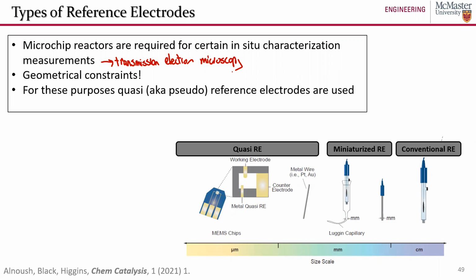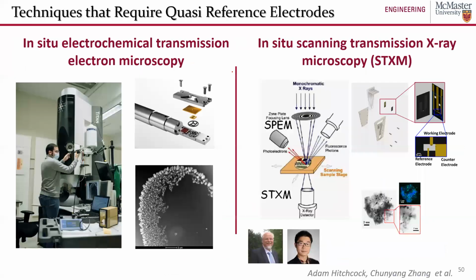Now, because these microchip reactors are so tiny, there's no way we can get a 1 to 2 millimeter silver chloride reference electrode in there, for example. So we use what is called a quasi reference electrode, and it allows us to overcome some of these spatial restraints. I mentioned that they're generally used for transmission-based measurements.